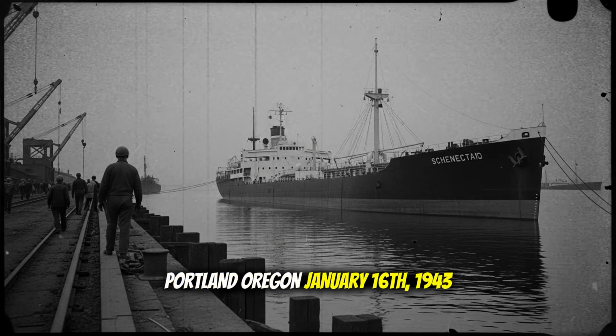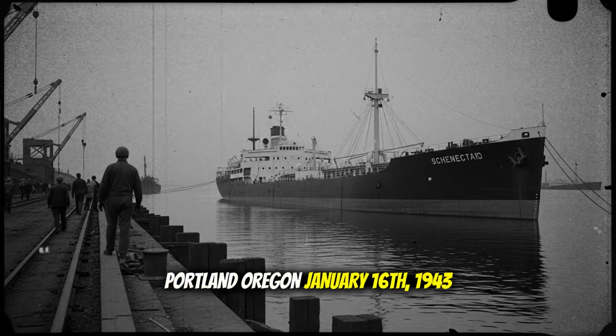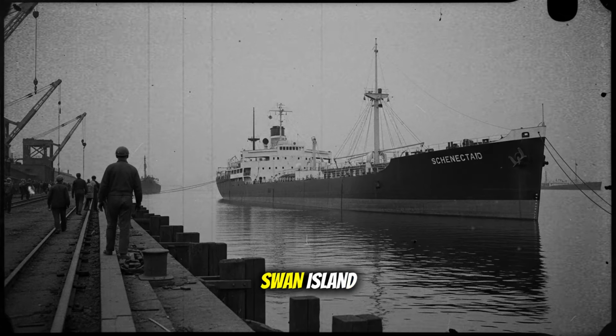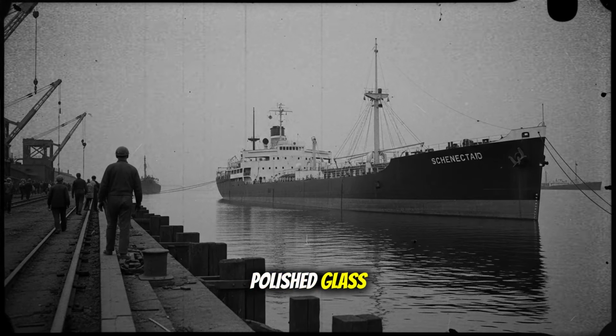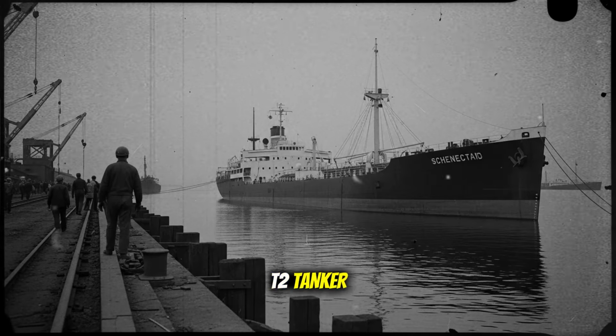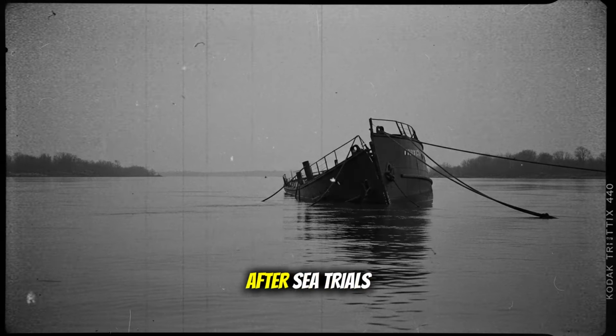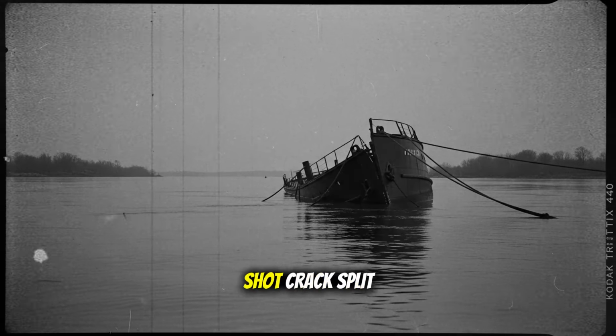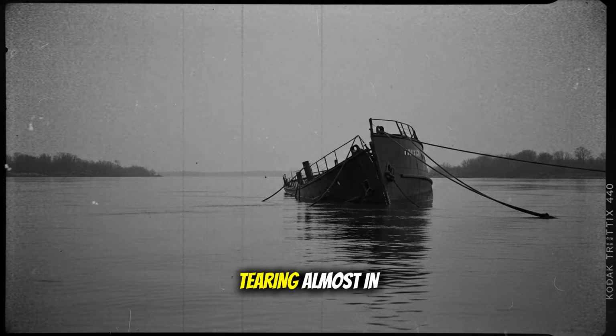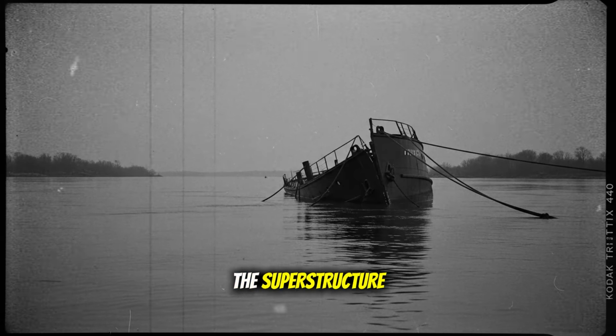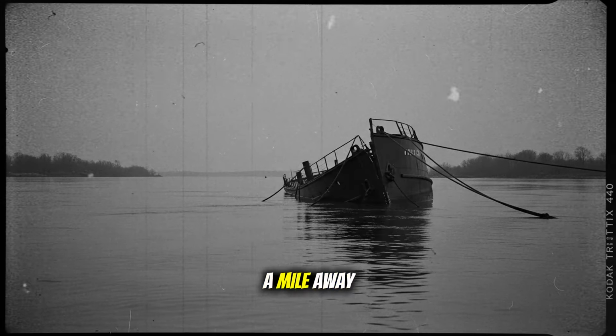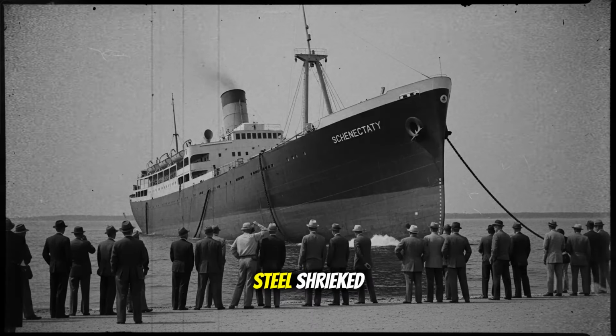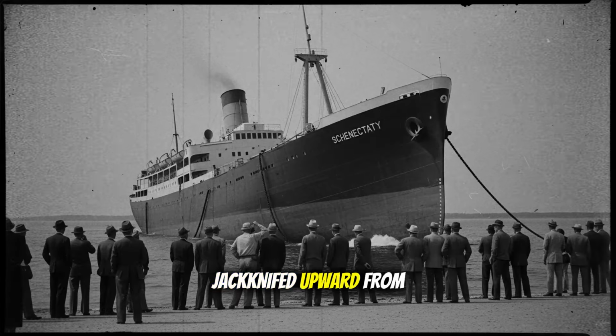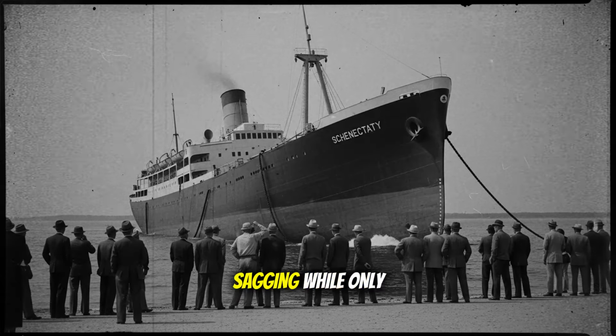Portland, Oregon, January 16, 1943. Dawn broke over Swan Island with water like polished glass, a brand new T-2 tanker moored quietly at the fitting dock after sea trials, when a rifle shot crack split the morning and then the ship itself, the SS Schenectady, tearing almost in half just aft of the superstructure with a noise heard at least a mile away. Steel shrieked as the hull jackknifed upward from the river, bow and stern sagging while only the